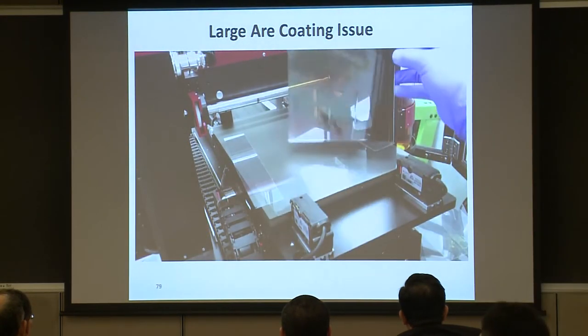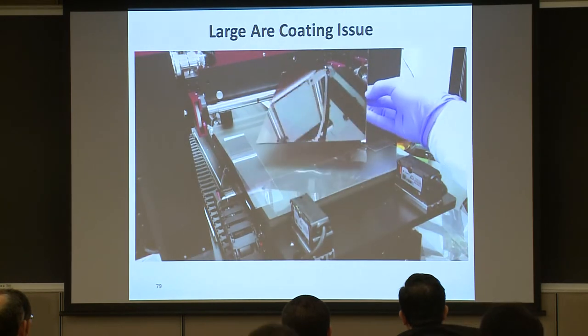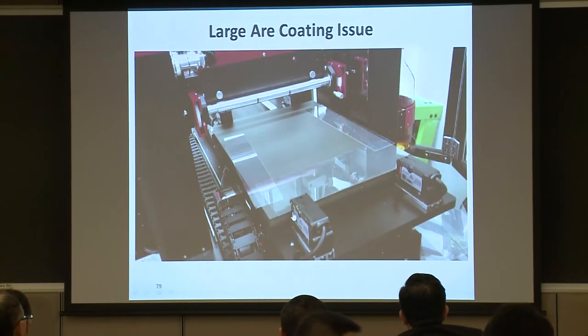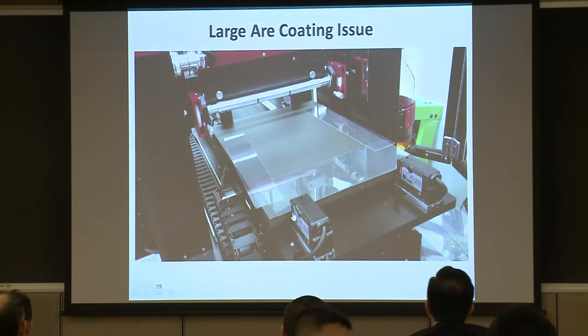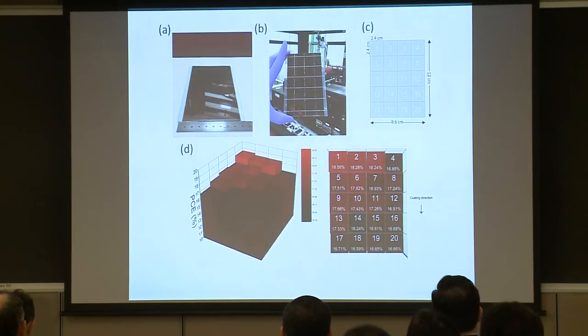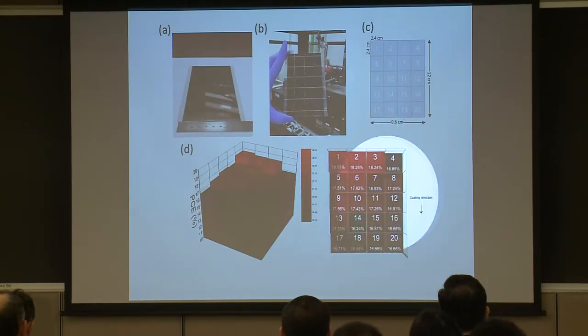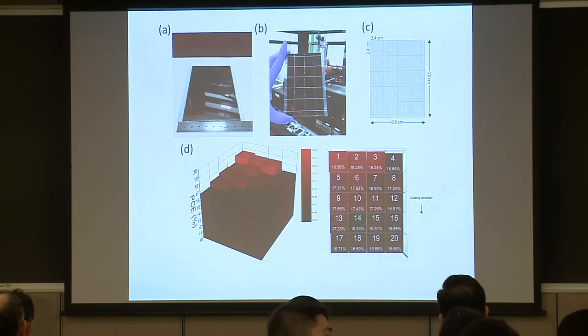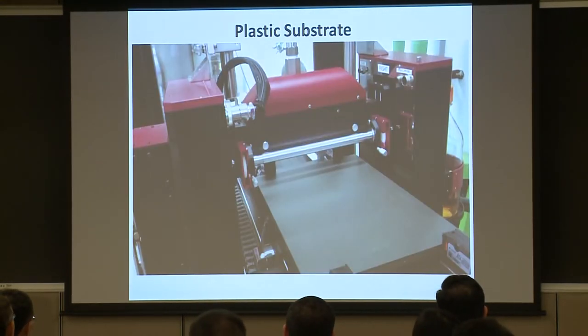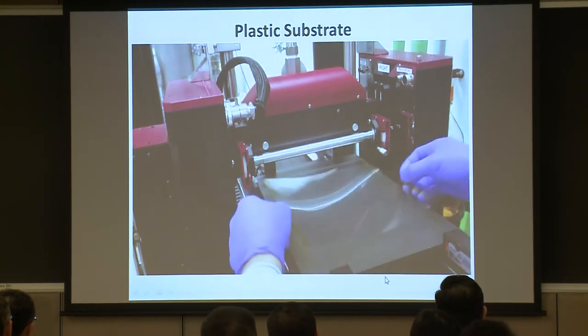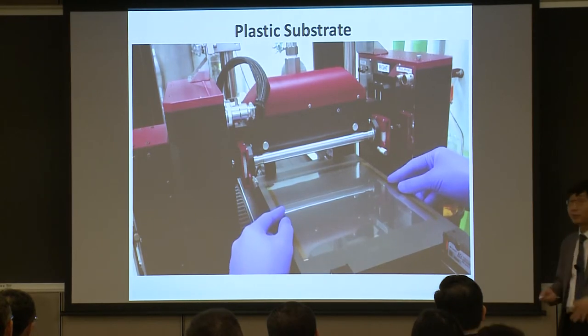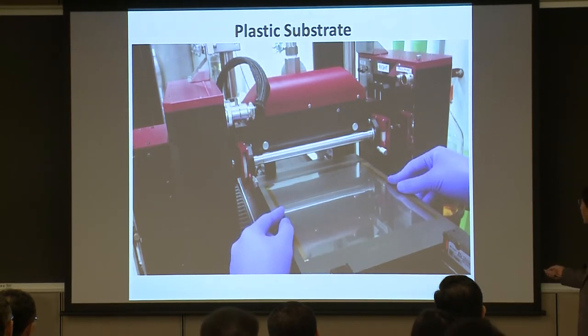And also, I think this is a very excellent technology. My student developed this, spending about 1 year to develop this coating solution and method. And then we can get an efficiency of around 17% as the average PCE. And also this method is very good for flexible substrates. Even at room temperature, we do not heat up the substrate.